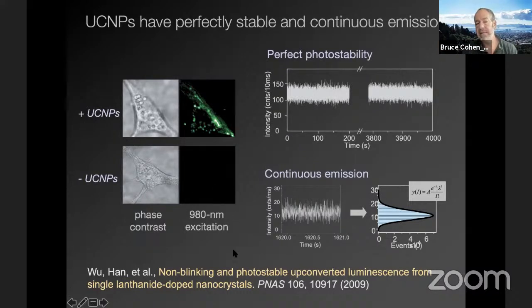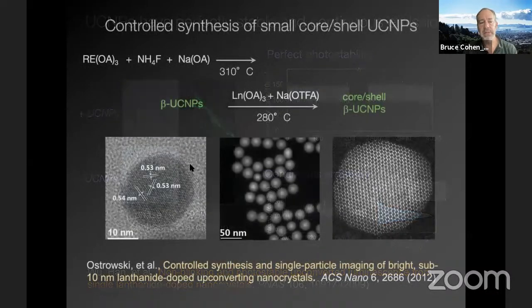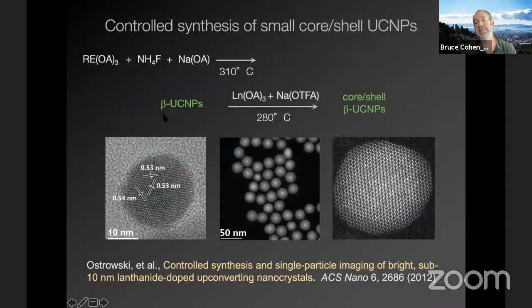And there were a few other things we discovered, like these don't blink, but this really set us in motion in trying to pursue these materials. And we had to work out a synthesis. One of the joys of this material is that within this synthesis, you can dope into the nanocrystal pretty much any lanthanide at any amount.